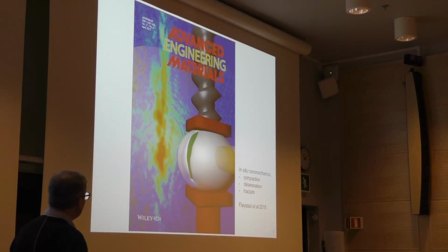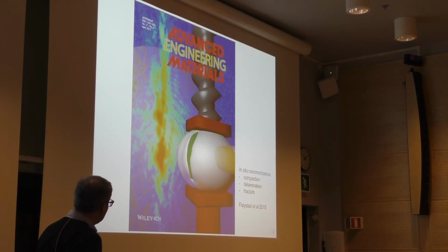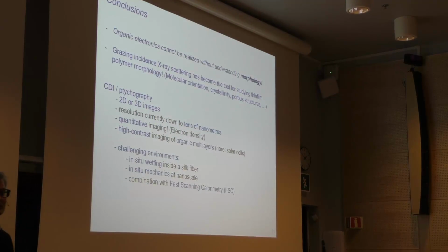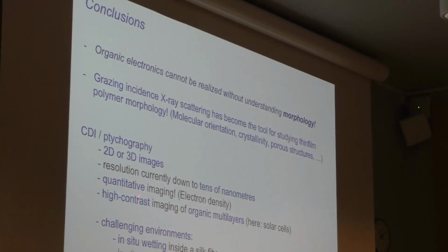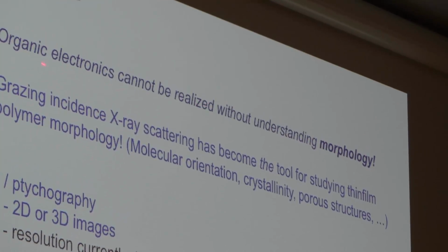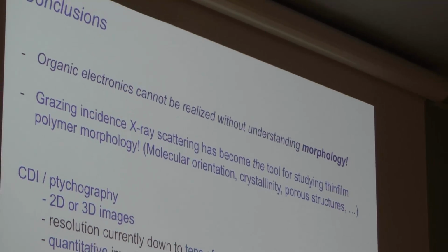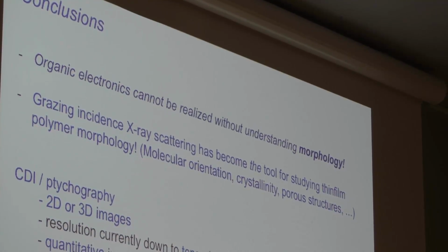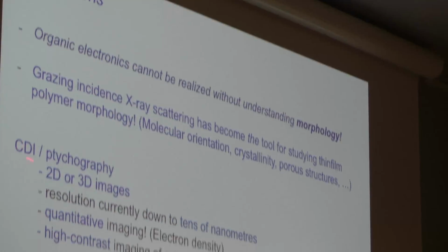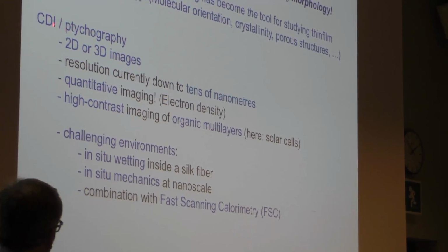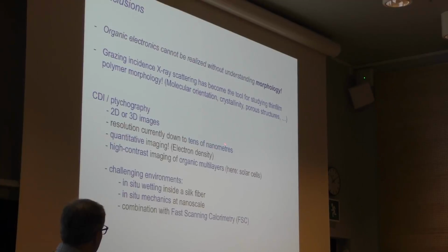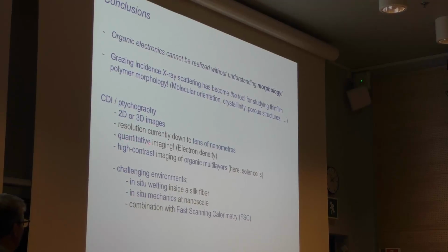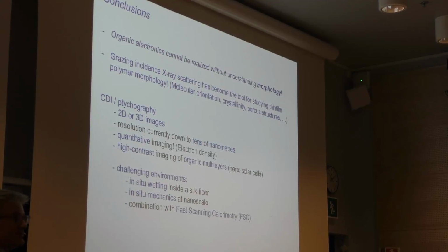We have also been doing a bit of nanomechanics with squeezing balls using this setup, but that I will not go further into today because my time is out. So in conclusion, I think that organic electronics cannot be realized without understanding morphology. And I would also emphasize that grazing incidence X-ray scattering has become the tool for studying thin film polymer morphologies. And then in the last part of my talk, I was talking about coherent diffractive imaging, which has a resolution currently down to tens of nanometers. It is quantitative and high contrast, and it can be used also for in situ studies.